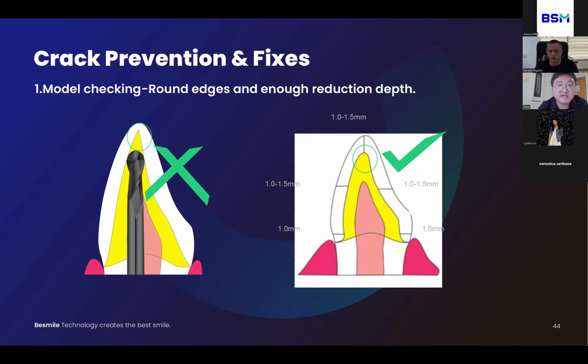So for the anterior teeth, the minimum size of the incisor part is 1 millimeter. And there are also some requirements about the thickness of the reduction. For the incisor part, the reduction is supposed to be more than 1 millimeter, from 1 to 1.5. And for the cervical part, at least 1 millimeter.